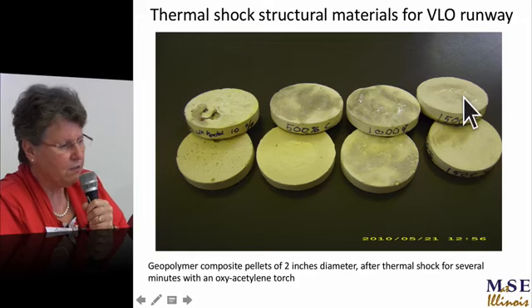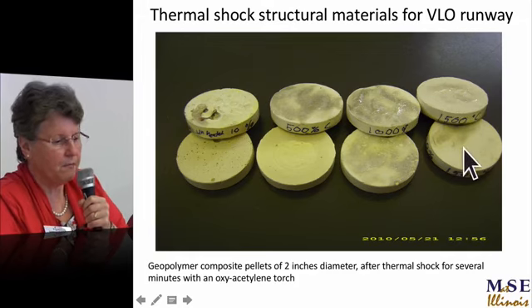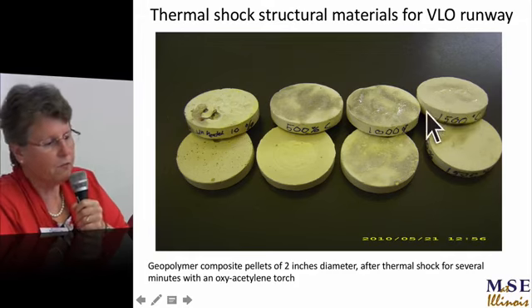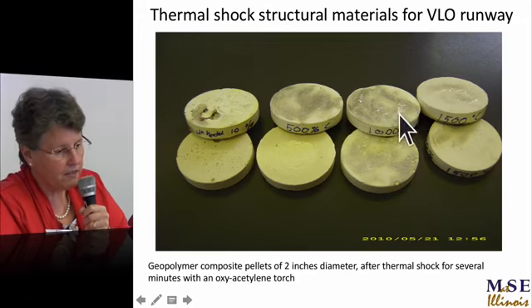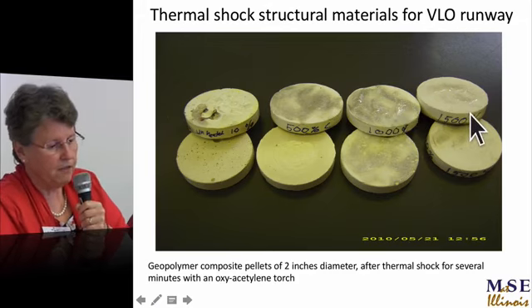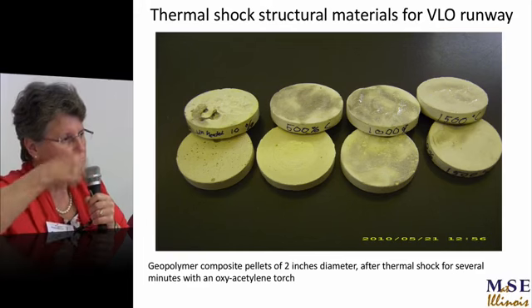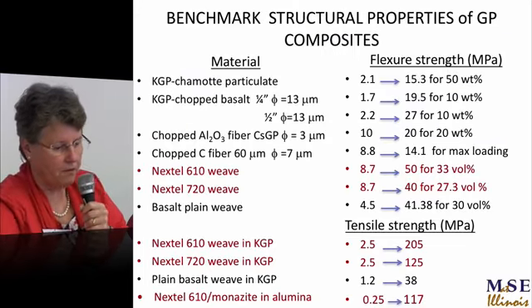Well, this was cesium geopolymer. With a bit of water, a glassy phase comes out, but at 1500 C, 5 minutes with an oxyacetylene torch, nothing happens.